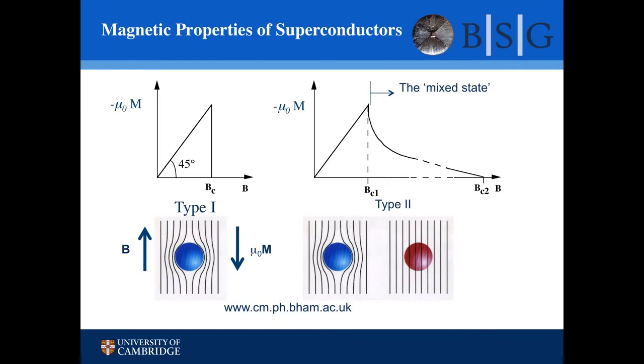And materials that collapse at some well-defined field here are called type 1. Type 1 superconductors are pretty useless for applications. Fortunately, there's a second type, type 2, and rather than superconductivity collapsing at a well-defined field, it gently goes away. And this upper critical field here that superconductivity disappears at can now be more than 200 Tesla. And we'll talk about fields and their size a bit later on.